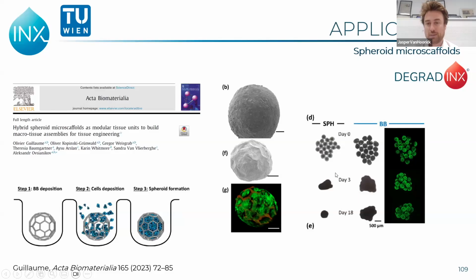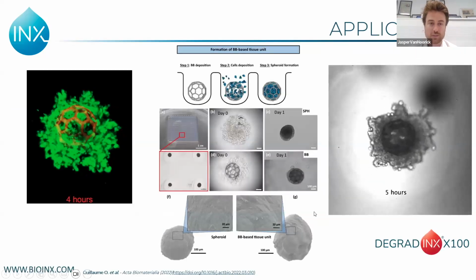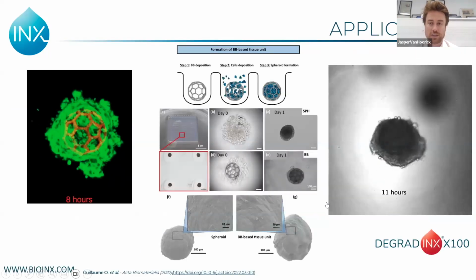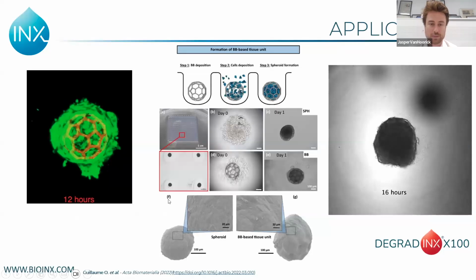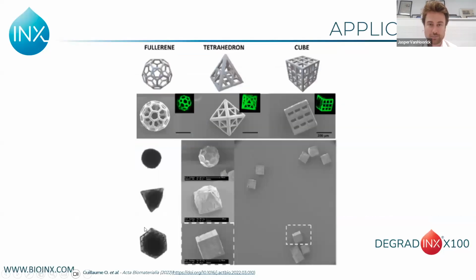Why do they want to do this? Because if you have normal spheroids and you put them in culture together, they will fuse, they will form a necrotic core, and they will shrink again. If you put your spheroids inside these cages, you can inject them, they will fuse, but they will not shrink because they're precluded from it. And in between these different cages, there's still enough space for nutrients and waste to transfer. You can see here that in 24 hours, your cells take up the shape of your 3D printed structure.